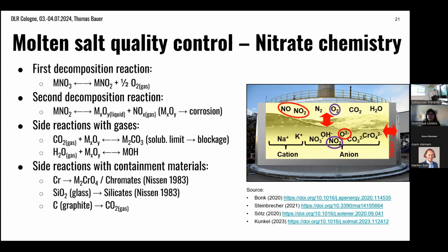So as I said, the salts are rather reactive. They react with a lot of things. They react with CO2 to form carbonates in the salt. They react also with water, maybe not in the short term, but in the long term, to form hydroxides. That's a rather slow reaction, but it happens for steam or water in contact. And then we also have chromium, for example, from the steel, dissolving in the salt.